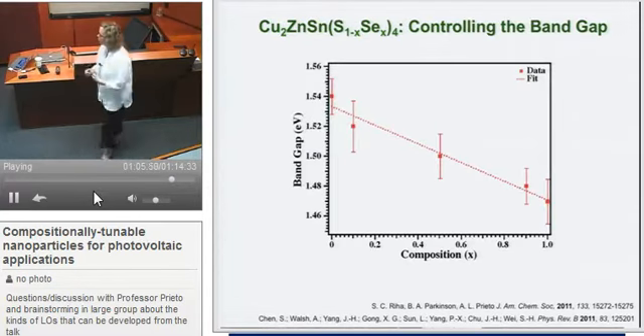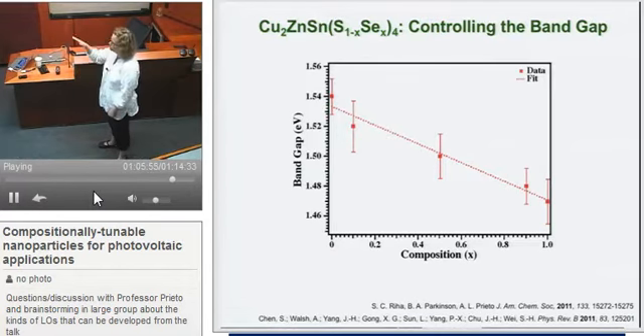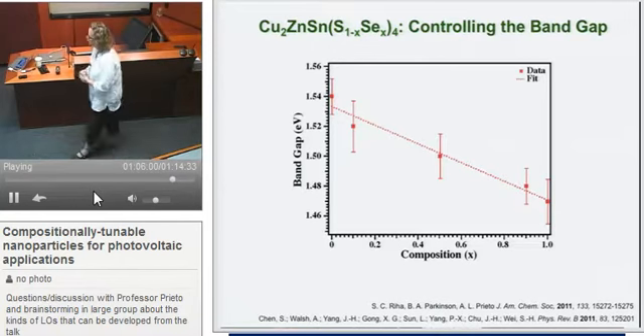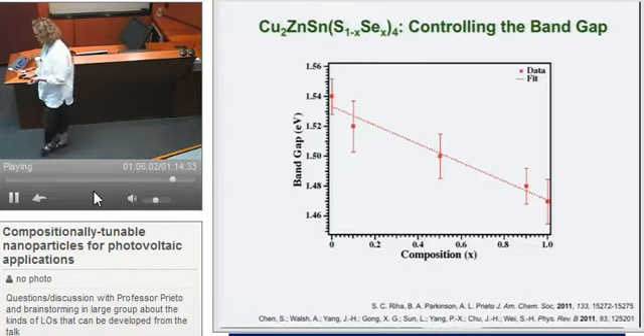So again, in terms of measuring the band gap using UV-vis, multiple batches from different days and different bottles, the trend again decreases, but we never get down anywhere near 1 eV. So the band gap doesn't change a lot, at least for these nanoparticles. So we wanted to know, selenium must be doing something, and we're trying to figure out what that is.